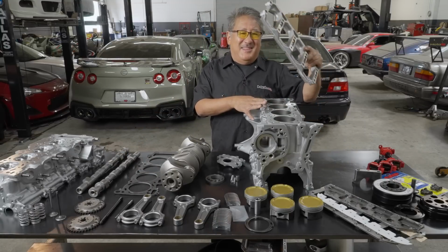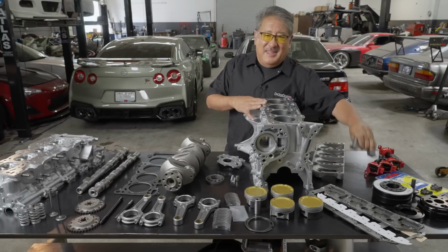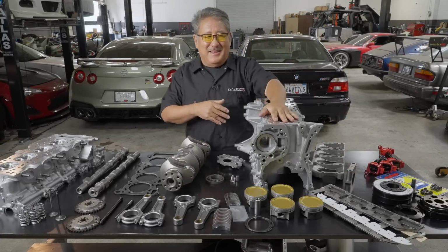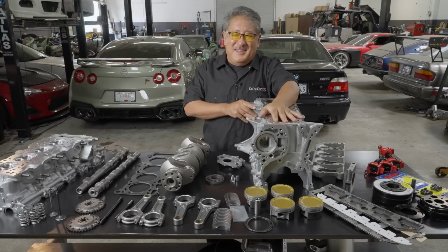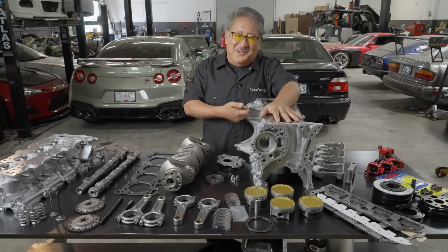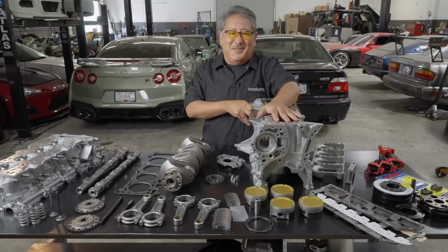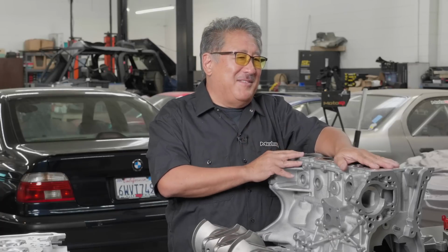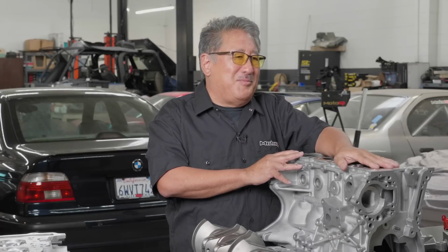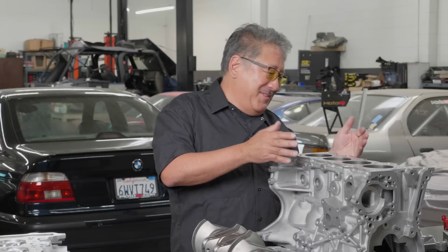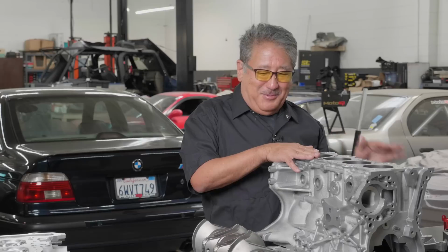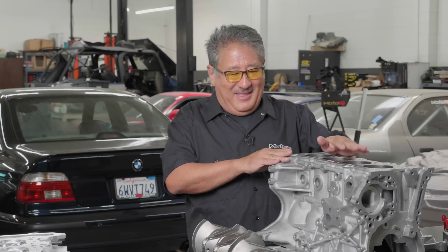We cryogenic treated the girdle and the main caps, and sometimes you see dimensional changes because you're changing the crystalline structure of the metal. Things move around and grow. So we carefully measured the main bores to see if they needed line boring after cryo, but everything was okay. And when we tightened everything down with the studs, the main bores were round and just about the minimum of Nissan spec, which is good for bearing clearance and maintaining good oil pressure. So everything was cool with the block. Everything's pretty strong. Pretty happy with how the block came out.